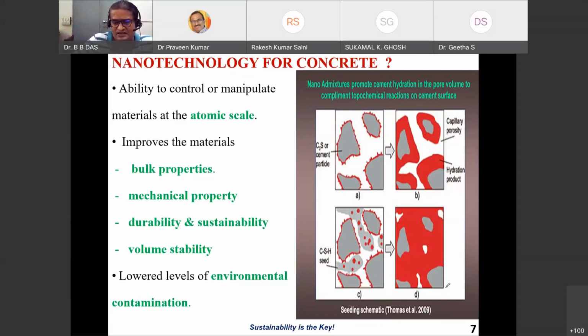Now, the right side picture, the D picture, you can see the hydration is complete. Let us assume the hydration is complete. You can see there are unreacted cement grains as in the previous picture, but you can see all the white patches are now covered with the hydration products, and that is what I need. That means I have least porosity because of the additional hydration products, and there is no continuity of the pores. You must be knowing the pore continuity is zero here. There are some discontinuous pores, but no continuous pore. But here you can see a lot of continuous pores are existing. So that is the advantage when you add nanoparticles into the cementitious system.